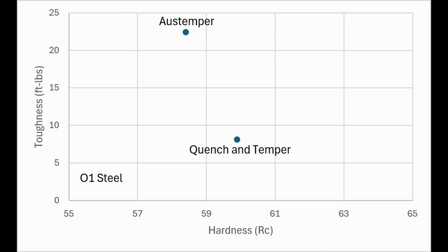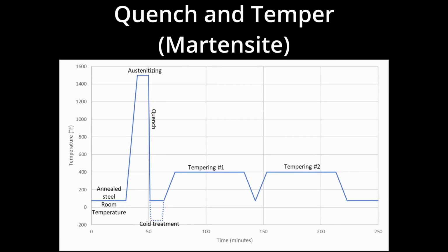So what is Bainite and Austempering? What an Austemper is, it's similar to a quench and temper. With a quench and temper, we austenitize the steel at high temperature, like 1500 degrees Fahrenheit or so. Then we quench down to room temperature, or approximately around room temperature, and then we temper at a lower temperature like 400 degrees Fahrenheit, 200 degrees Celsius. Usually that's done at least twice.